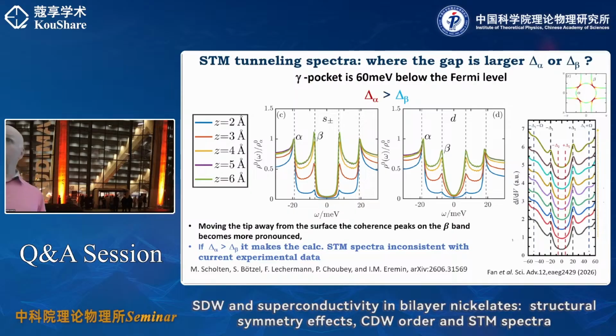My suspicion is that they accidentally did SIS tunneling, because effectively they picked up some part of the superconducting film, and then they measured an SIS junction. And they saw a very different spectrum also, because if you look, they have a very flat region below, and they had really zero, which is very unusual. It's very unusual behavior of the dI/dV, and it would also be one of the things, but nobody did the calculation of what you would expect in this case. So this is something we think about doing, but to do SIS, you need more effort. That's true. You need more variety, more different surfaces, different tips to make a conclusion.